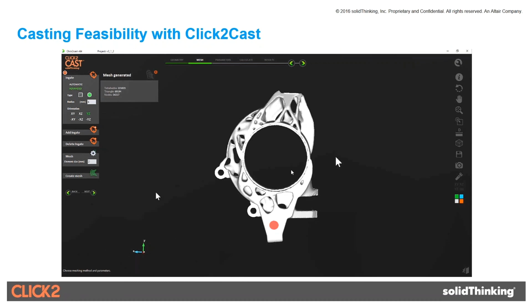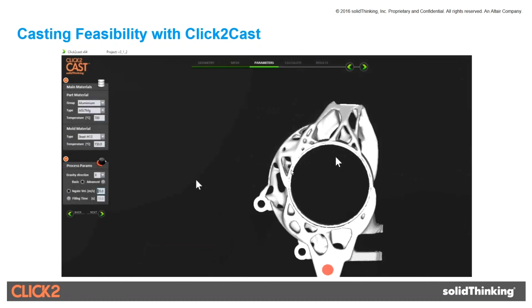You had a lot of turbulence when you had two gates. So finally, we went ahead and had a single gate at the bottom to feed this casting, which was much less. And we also evaluated, and this is how we use Click2Cast.